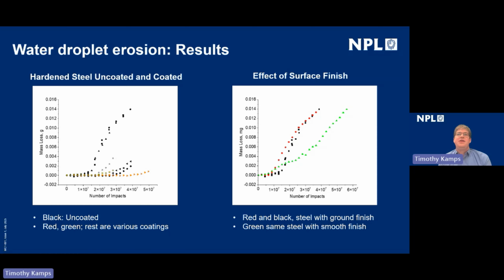rate of mass loss. So in systems where it may be acceptable to have a mass loss after incubation before the part needs to be exchanged or serviced, it may be sufficient just to change the surface finish, rather than use a coating. And again, this comes down to what the acceptance limit is in the specific application, and also the cost-benefit analysis around the time interval on the servicing of these parts.